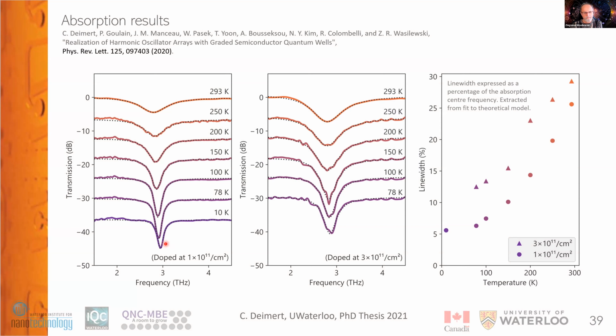With that, we managed to demonstrate the plasmon transitions, which are extremely sharp and retain their sharpness pretty much to room temperature. So it shows here the line width in percentage. Basically, it's a ratio of the line width to the energy of the transition. And in order to get strong interaction, which is what we need for polaritons, we need about 15% or better. And you can see that we are well below 15% up to almost 200 degrees Kelvin, which was pretty stunning for everybody working in this field at that time. So this was published in 2020 in Physical Review Letters, and we basically took it from there, going towards more experiments and learning how to make those polaritons.